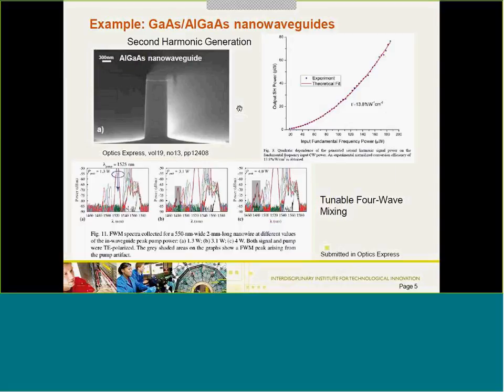Now, we have all these nice building blocks, so how can we assemble those to actually make a device? Here's an example of a nano waveguide that we've made off of gallium arsenide, aluminum gallium arsenide devices. We have a standard recipe for GaAs etching, but for nano waveguides, we need to make sure that the verticality is almost perfect and that the sidewall roughness is really low. So we've modified our existing recipe to etch these nano features. In doing that, we can make some second harmonic generators or four-wave mixing devices. So we dry etch the mask, we dry etch the waveguide, and there you go. It's not very complicated, but you do need to adapt your building blocks to whatever device you want to make.